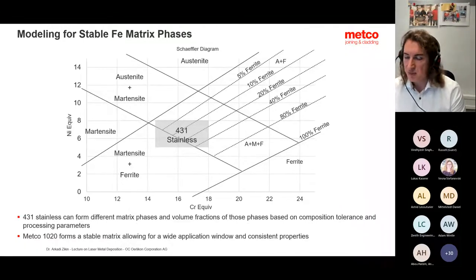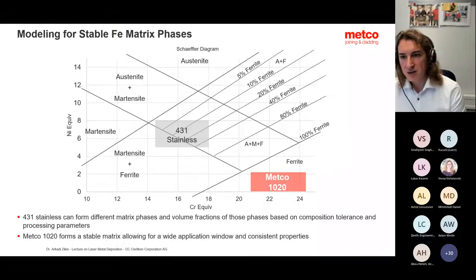Typically, if you work with this type of 420 or 431, directly after laser cladding deposition, you are over 50 HRC, which gives you quite a nice wear resistance, but at the same time, it has an impact on your corrosion properties. So developing material, which is also very important, nickel-free, where nowadays it's getting even higher importance, you can